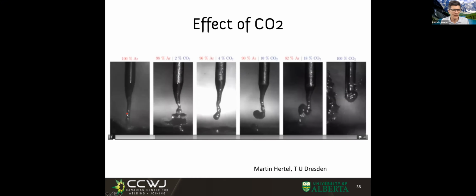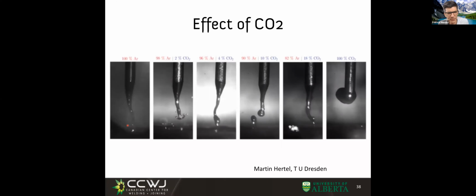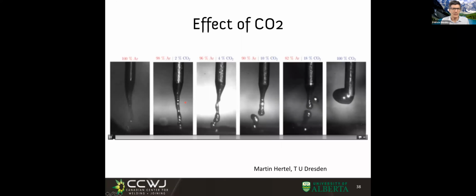You get to see something else in this set of videos too, that is so awesome. You get to see that in 100% Ar, the droplets go pretty straight. Is it exactly straight? No, nothing is ever exact, but it's fairly straight. But as we add more and more CO2, you get to see how the droplet sometimes detaches to the side. In this case, that droplet here is definitely going to this side.